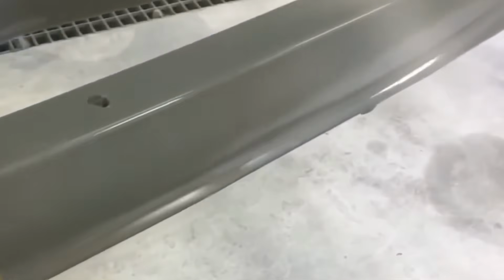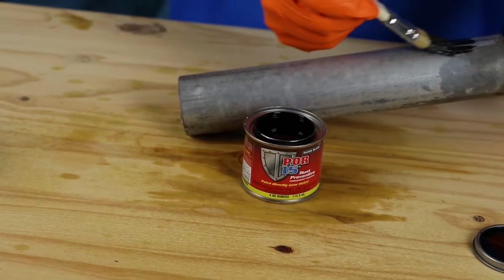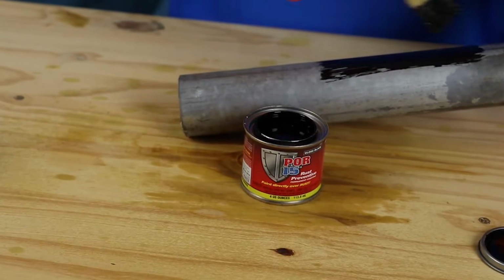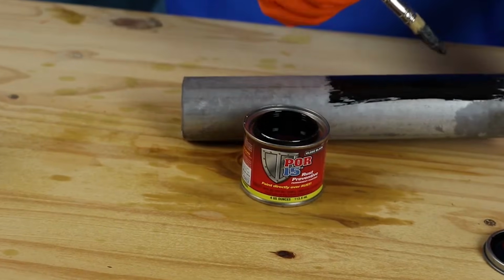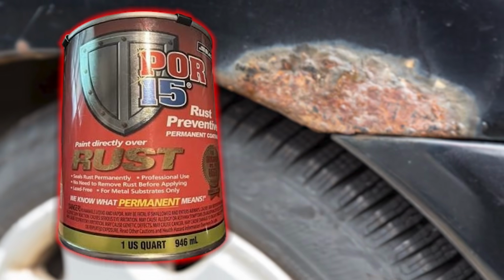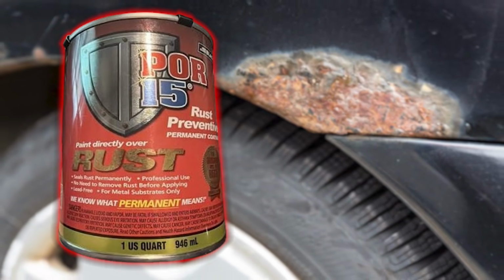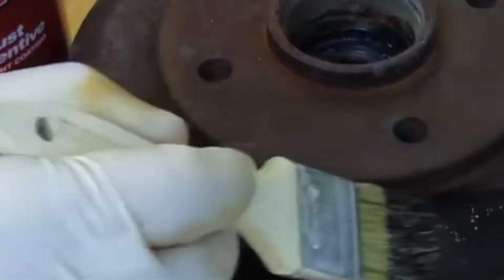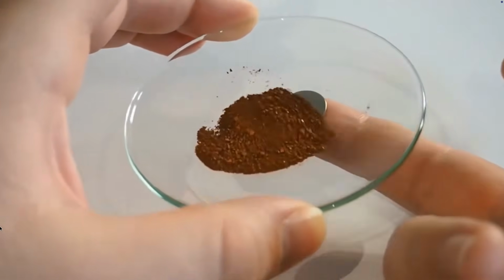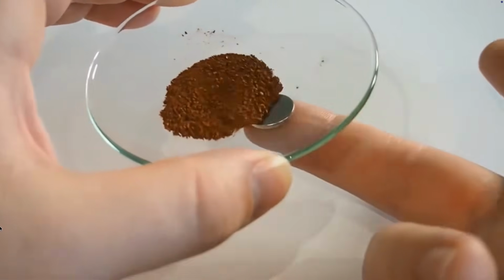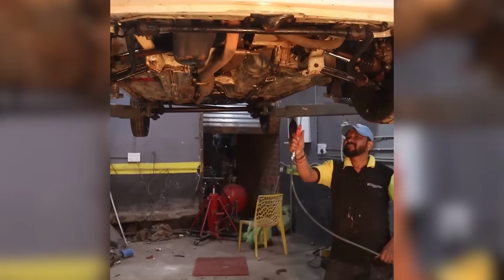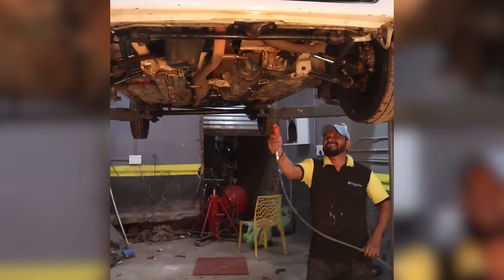It uses moisture as a curing catalyst, rather than treating moisture as a contaminant to be excluded from the treatment process. Every other product in this investigation works better on dry rust than on wet rust. POR-15 works better on rust that has ambient moisture present. The formula reacts with iron oxide and atmospheric moisture simultaneously. The reaction produces a coating that becomes harder and more chemically resistant as it cures.